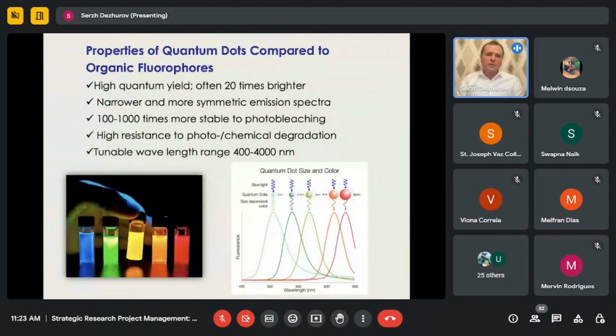And third, one of the important properties of quantum dots, is very good stability to photobleaching. It's about 100 to 1,000 times more stable than any organic luminophores, because they easily photooxidize by oxygen from the atmosphere, and after that destruction, photobleaching has happened.